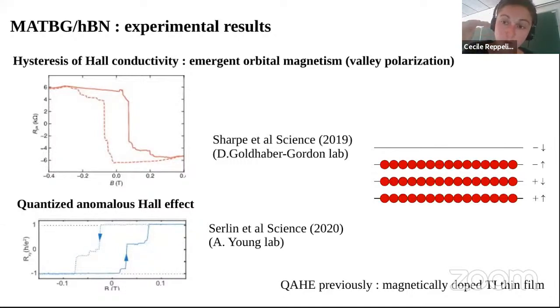So the topology was coming from spin orbit coupling in those materials, and then they doped them with transition metals, so impurities that explicitly break time reversal symmetry. Here, the origin of the time reversal symmetry breaking is very different. There's no doping. It's spontaneous, and it's a material with only carbon atoms. So after this phenomenology, let's go into some microscopics.